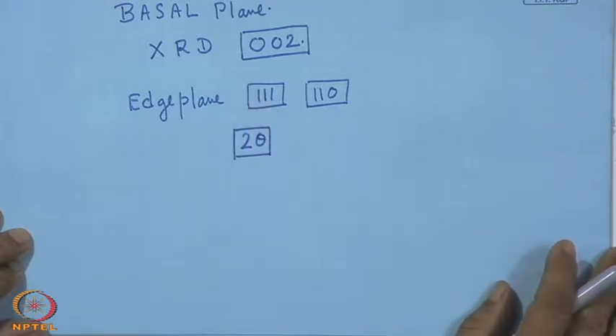So, these are the few things one has to look at while going for this MoS2 coating deposition, because ultimately the aim is that it is the best possible mechanically functional coating. So, from this XRD we can get fast and very preliminary information, but it is very, very useful in telling whether we are on the right track in the whole deposition process, and whether the process parameter selections are proper, which may finally lead to one of the best performing coatings.